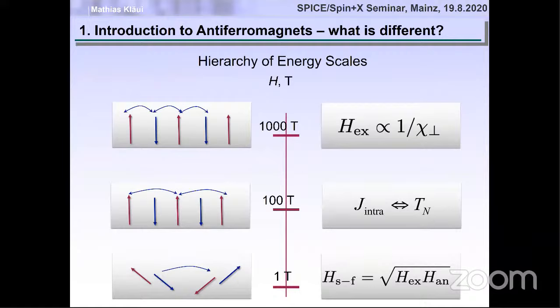I would say that we should understand that there is a phenomenological approach and a microscopic approach. And the phenomenological approach should not really contradict the general physics. It does not contradict the general physics. And in the macroscopic approach, what we do, we average over large macroscopic volumes. This is physically small, but macroscopic volumes. And when we do this averaging, we take into account all the microscopic exchange. And when I introduce these parameters like intra-sublattice exchange and inter-sublattice exchange, both constants include contribution from all kinds of microscopic exchange which we can find in the system.